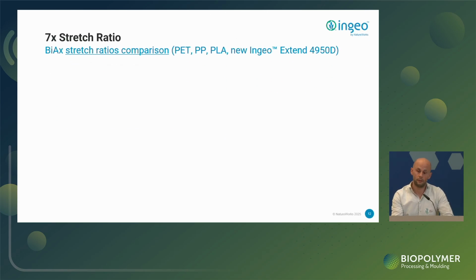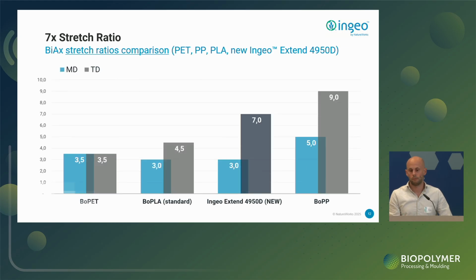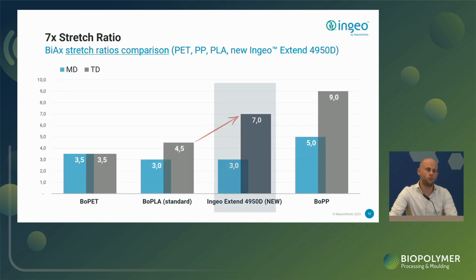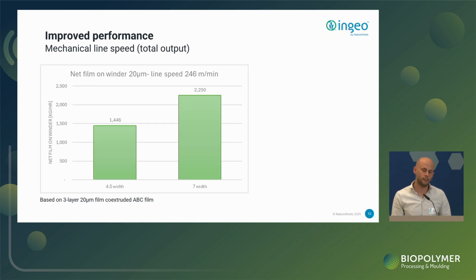Talking about productivity. Today, a standard BOPLA film is stretched at a maximum of 4.5x typically in transversal direction. And what you see is that by adjusting the formulation with this new grade, we have been able to increase the TD stretch ratio to 7x. So that's a major improvement. It's really significant. And we are trying to further improve that in order to reach really the target level of BOPP films, which is stretched up to 9x. And what that means for the productivity of the film, you can see on the next slide.